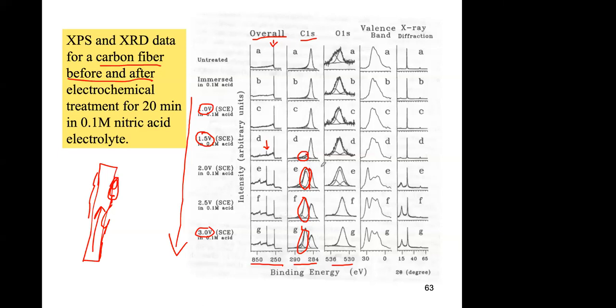The oxygen also changes with time. In the oxygen, you're seeing one type of functionality here. Here you have like two functionalities. I don't like oxygen too much. Sometimes it's difficult to observe, but here you can see that you have like one oxide formation. You see only one peak, maybe it's one type of oxide that you're forming with carbon.